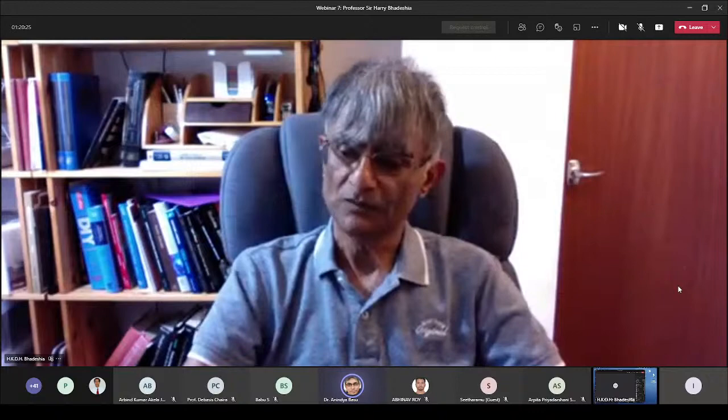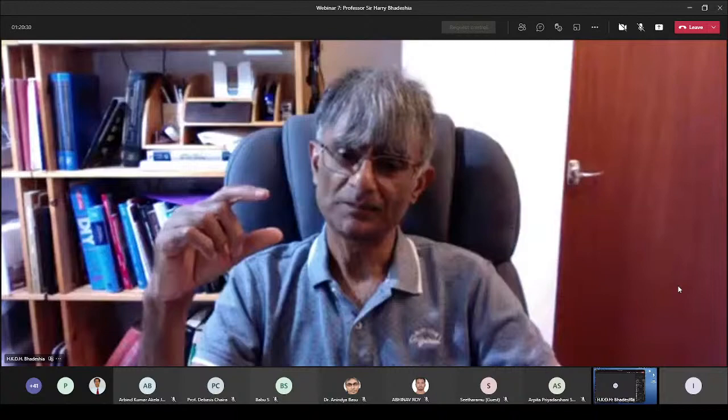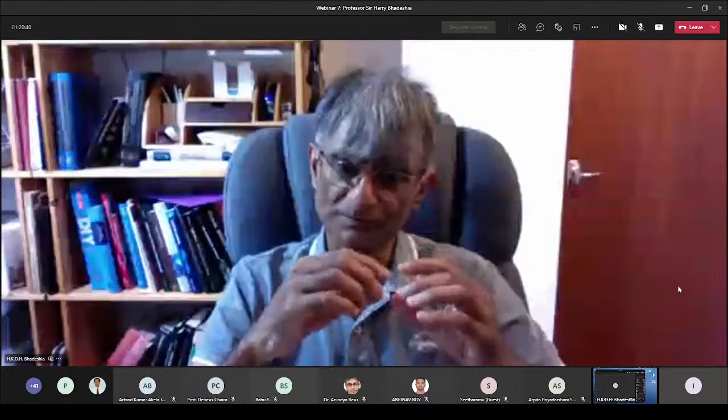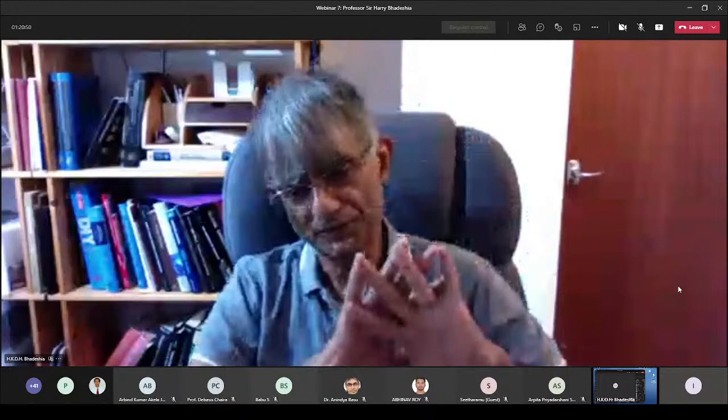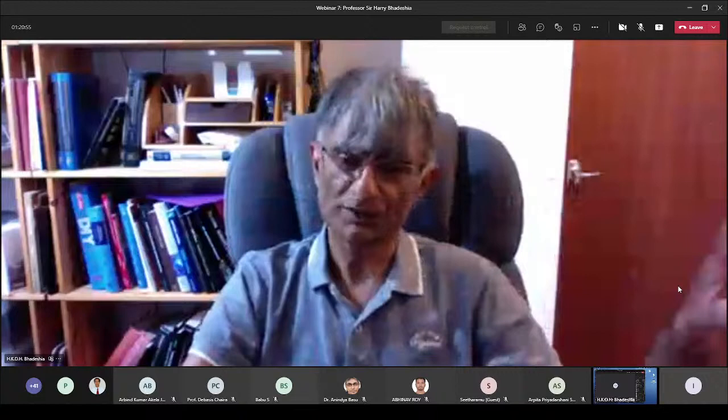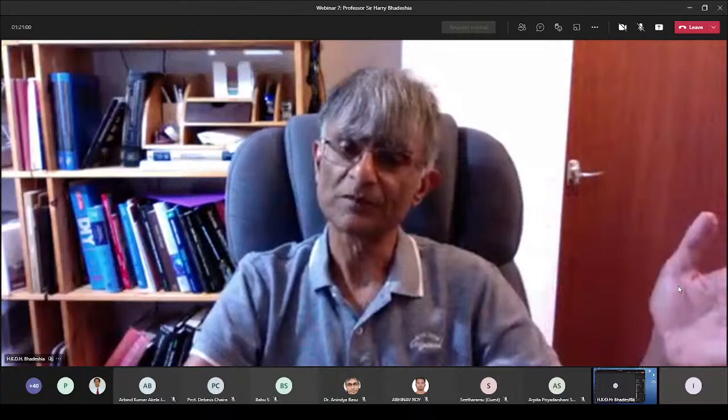Yeah. So the term acicular ferrite is used in two ways. One is in welding alloys, where the plates of bainite form on non-metallic inclusions, and therefore they form a very interwoven structure which improves toughness. But in low carbon wrought alloy, the sort of steels you produce in hundreds of millions of tons, the acicular ferrite is basically bainite. It's no different from it.